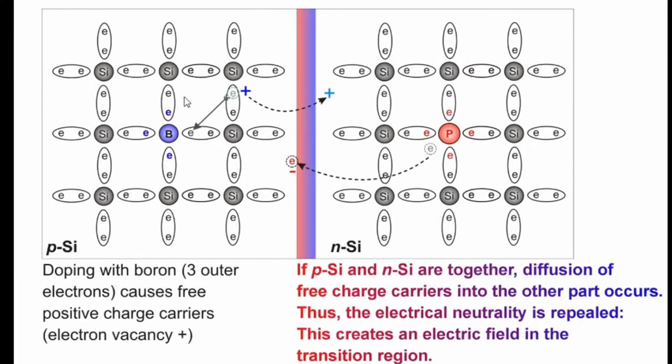There's also the other way around, so-called P-silicon. There you dope with a boron atom. This boron atom only has three outer electrons. That means in order to complete the links in the tetrahedral formation to the neighboring silicon atoms, there's always a missing electron. What do you do if you miss something? You can borrow it from a neighbor. That's the case here. So he is missing something. So now you got it from the neighbor, but then the neighbor is missing something. And therefore it's called a missing electron or hole, like a virtual positive charge you have here.